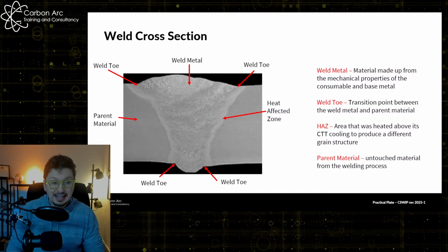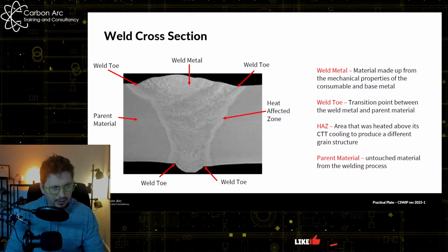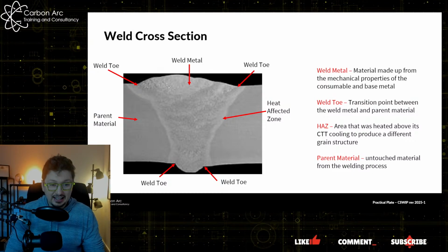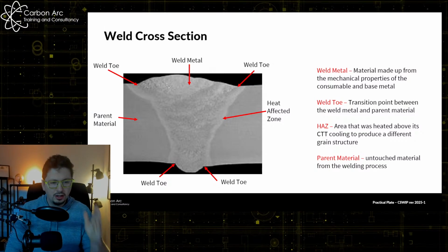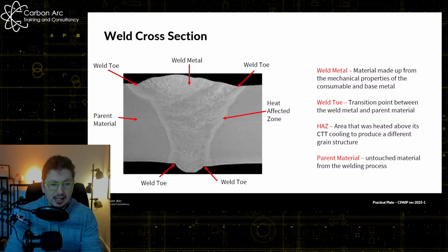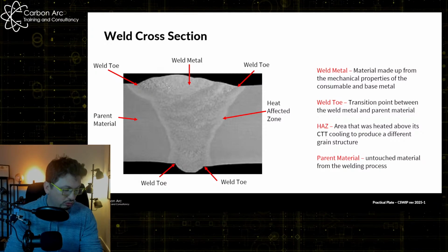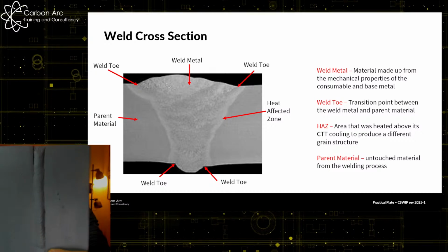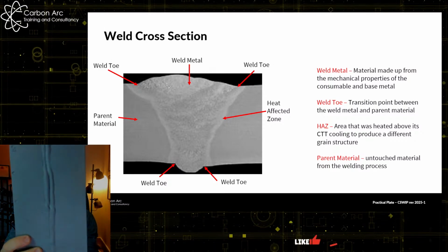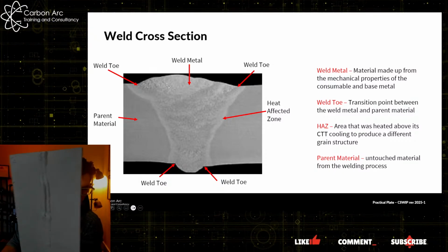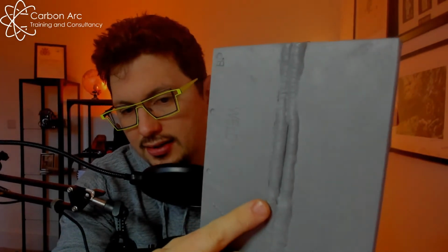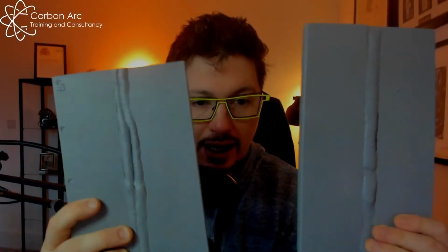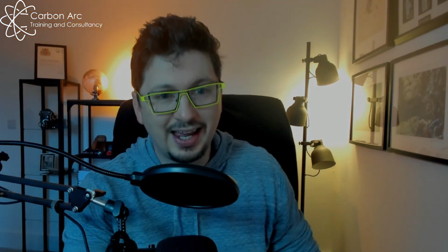Understanding which defects are likely to appear in which area is also really important to make sure we identify our defects correctly. So things like slag, for us, are never going to occur directly down the middle of the cap of a weld. They will occur in the toes of a weld. So if you've got a single pass weld like this, you will not get slag appearing down the middle. You will get it in the toes. But if you've got a weld like this, where you've got two welds coming together, then you could get slag running down the inside. So knowing the difference between these two different types of welds and where we're likely to find it will stop you getting negative marks by calling up the wrong defect.